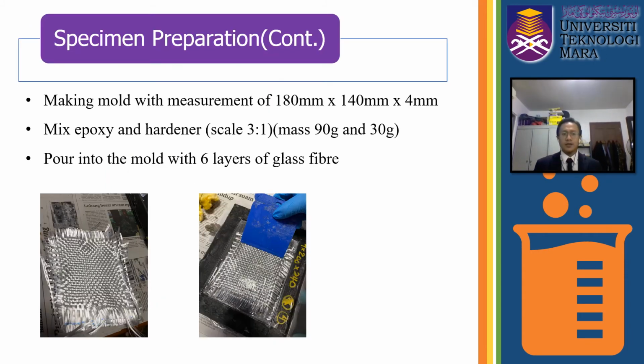For the specimen preparation, the first thing that I do is making a mold with measurement of 180 mm length times 140 mm width and 4 mm thickness. After I make a mold, I mix an epoxy and hardener with a ratio of 3 epoxy to 1 hardener, in a mass of 90 gram of epoxy and 30 gram of hardener. After I mix them and stir it well to ensure there is no bubble in my mixture, I pour them into my mold and I put the 6 layers of fiberglass in the mold.